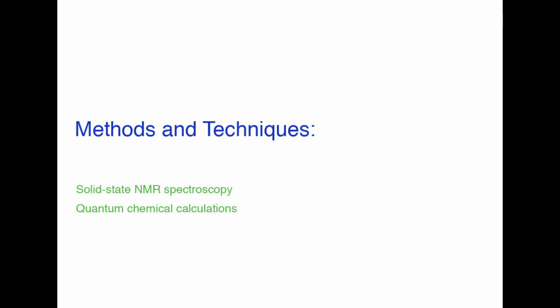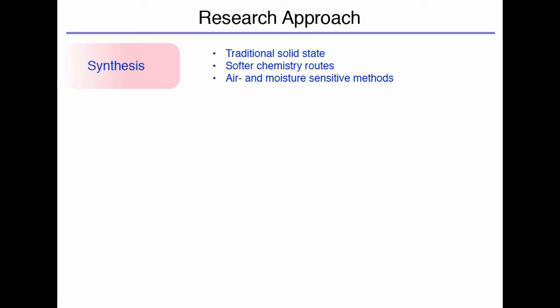So what are some of the methods and techniques that we use to try and understand this structure-property relationship? Well, the sort of research approach that I have in my lab basically starts with us trying to make the materials. So we try and make the materials in our lab using conventional solid-state chemistry methods. And these aren't particularly complicated. It's a bit like cooking, actually. You put your materials, you mix them, you put them into a high-temperature furnace, and you heat them for sometimes minutes, sometimes hours, sometimes days or weeks.